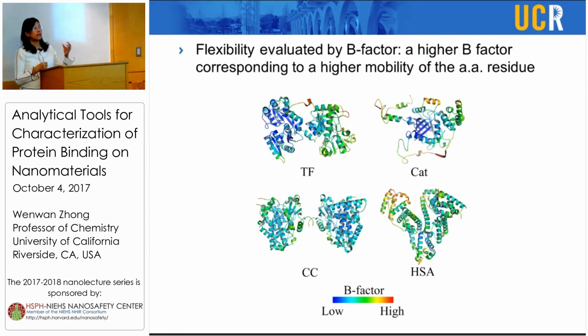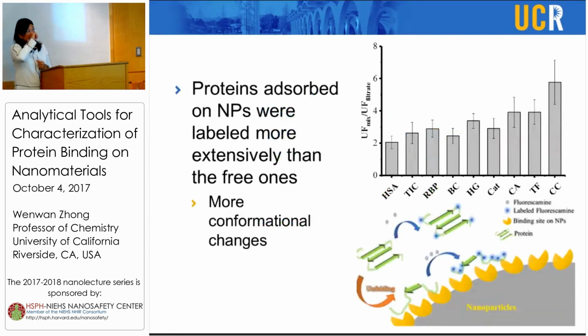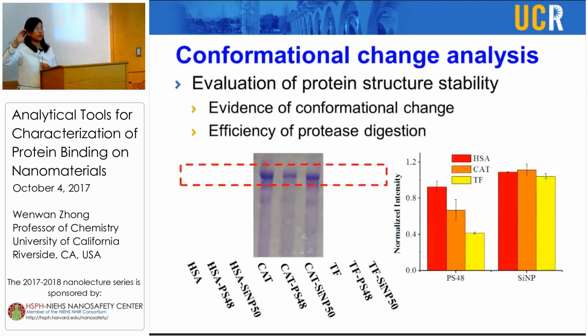And also, like I said, cytochrome C, although it's rigid, has a heme group. So that is another common feature that we find in the group of proteins showing high fluorescence change. What we think is that the labeling could be due to conformational change differences, because those will open up more lysines to be labeled. But more importantly, we want to confirm that, and so we use partial protease digestion.